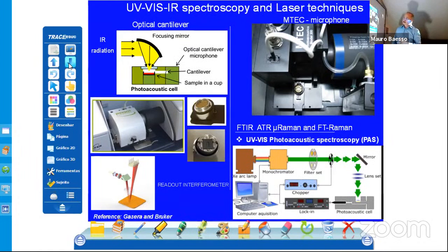Okay, just for those that don't have too much experience, I'm going to use a conventional photoacoustic spectroscopy. You have a modulated light inside a sample in a closed cell, and then you have the absorption of the light. If the light is absorbed, part of the energy can be transferred to heat, and the heat generated will be captured by a microphone that is positioned here, and then you synchronize with a modulation frequency, and then you can get the photoacoustic signal. So you get the heat generated after absorption of the light.